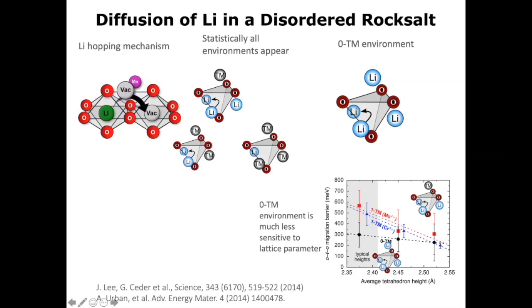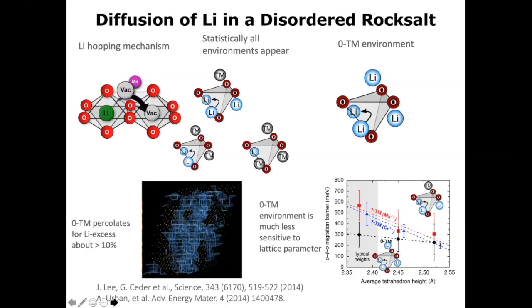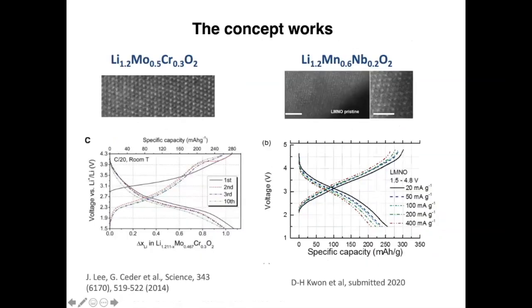So of course, migration through that channel by itself is not diffusion. To have diffusion, you need percolation of these channels. And what we found is that if we study random cation distributions in a rock salt, you get percolation when you have about 10% lithium excess. So this is the basic principle, right? In disordered rock salts, diffusion occurs through these channels and they statistically percolate through the structure. So you don't have a well-defined path like in a layered material, but you have these kind of tortuous pathways through the material. And this actually works.